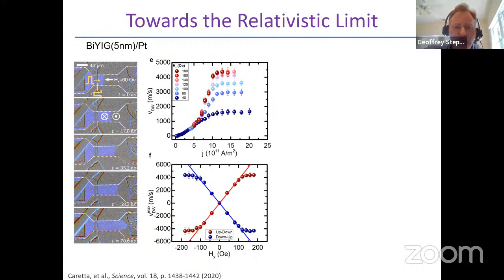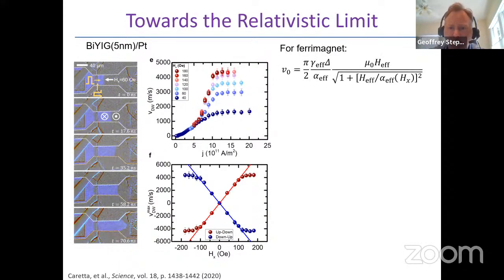But then we find, as we stiffen it more and more, the curves in the bottom here tend to plateau out. So there's another velocity that even if we add additional stiffening to the wall, we can't drive it any faster. That velocity turns out to be the maximum magnon group velocity, which we can infer from the magnon dispersion curve that we've measured. And again, let me just jump through this.